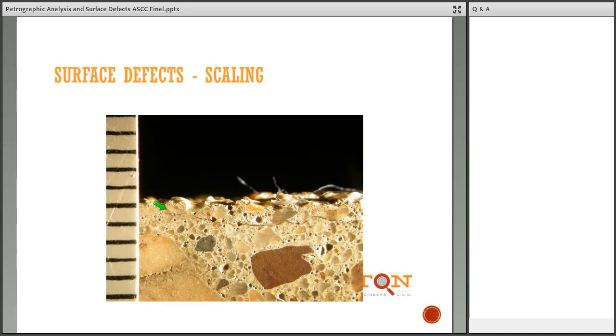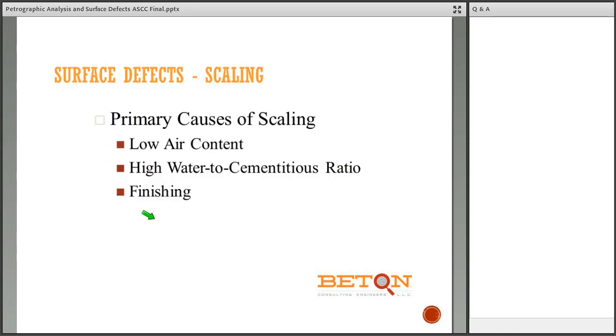And so basically we ran ASTM C457 spacing factors where it should be, and it's all the way up to the top, so it doesn't look like it was overly aggressively finished. So what next? You look at water-cement ratio, and that particular instance was found to be a higher water-cement ratio or higher water-to-cementitious ratio. Primary causes of scaling: low air content, high water-cementitious ratio, and aggressive finishing or early finishing.